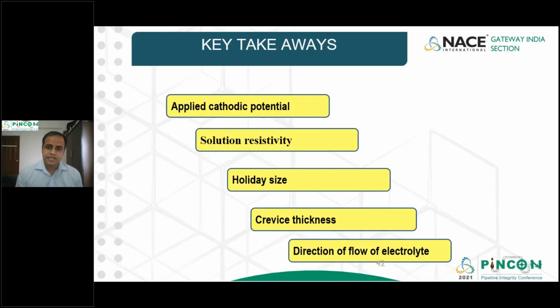With this, the key takeaways I would like to reinforce in the mind of all of you is applied cathodic potential, solution resistivity, holiday size, crevice thickness, and direction of flow of electrolyte are the key parameters that control your corrosion inside coatings, even with ICCP applied.